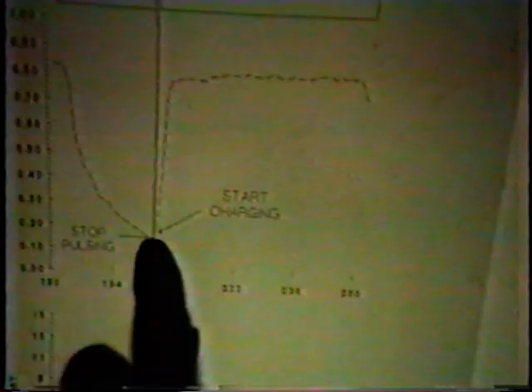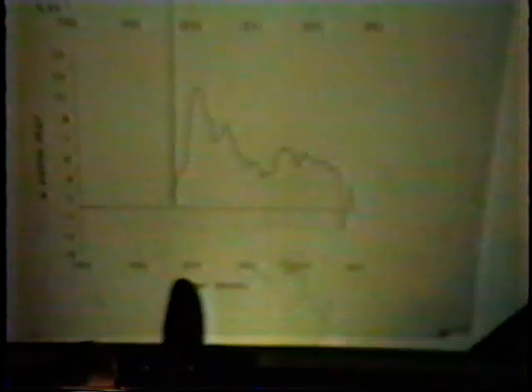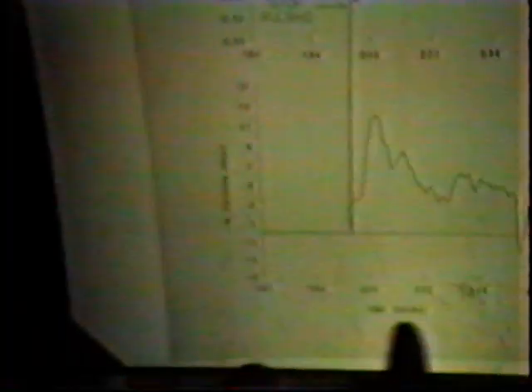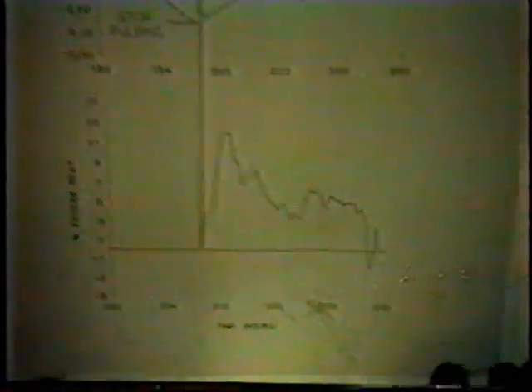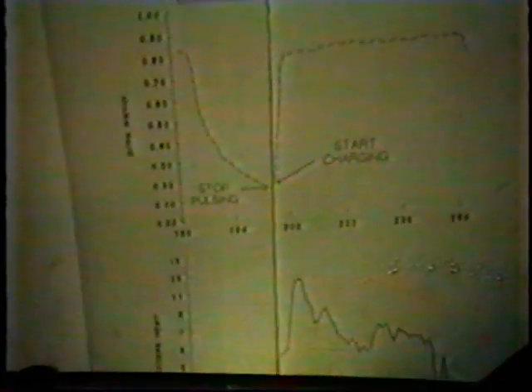And then when we got down here, we went into rapid charging and immediately got heat to the extent of about 10%. We have heats up to 19 or 20%. This is 1 burst. We had 5 bursts in the recent work, and you see this particular burst lasted quite a long time, from 208 hours to something like 240 hours, with those variations. During this time, of course, we were not pulsing. And the burst was interrupted by renewed pulsing. It would have gone on otherwise further.